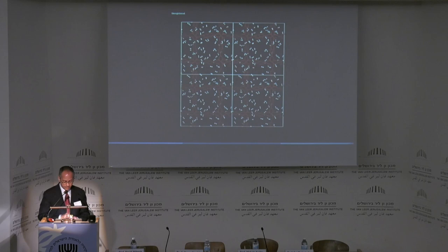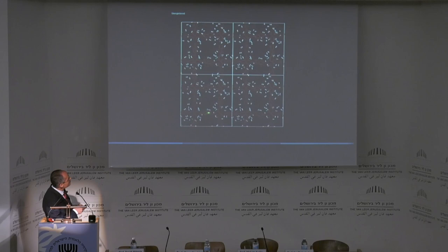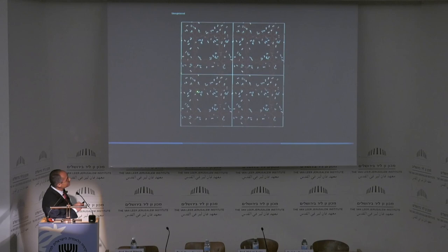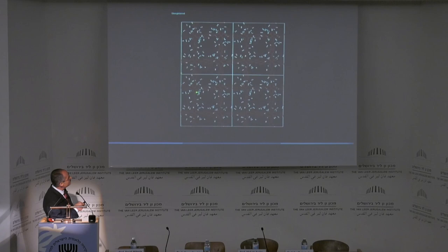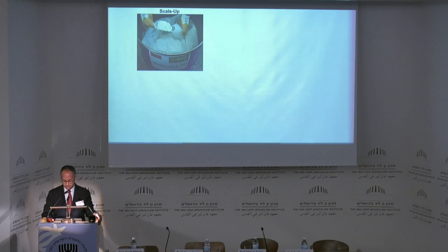One of the things that we wanted to do early on with this high porosity is that if you have adsorptive sites on the internal surface, now you can use them to attract molecules like hydrogen or methane, so that these gas molecules would be attracted to the surface and overcome the gas-gas repulsion. So that means I can compact gases on the surface without having to pressurize the material. And that was the first point of applications, that we worked with BASF to scale up MOFs to multi-ton quantities.